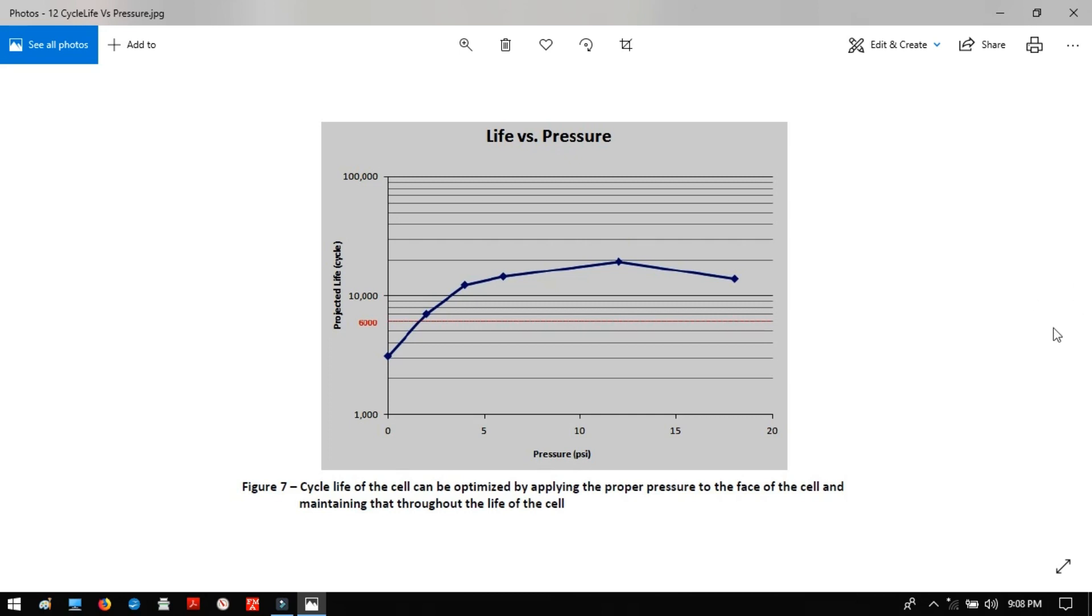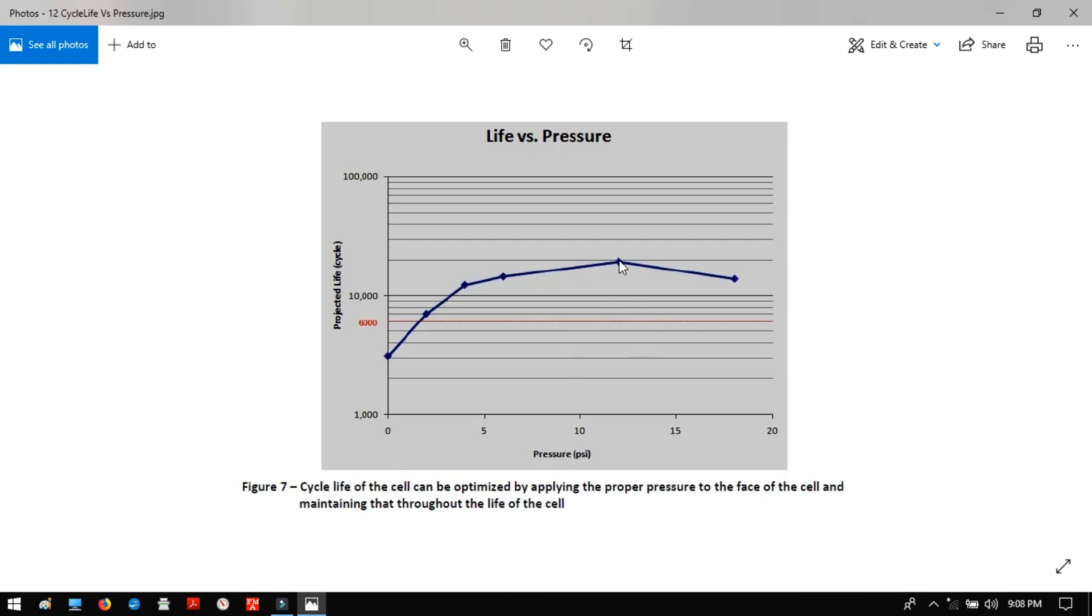And the last one I wanted to mention here is one that often isn't talked about too much, and that's the pressure. A lot of times these chemical reactions inside the cells in the anodes and cathodes and so forth has slight volumetric differences. And so in these pouch cells, these A123 lithium iron phosphates that I'm talking about here, we start off with so many thousands of cycles. But they actually, the anodes and cathodes and so forth, can physically change in size slightly as they get filled and depleted as the lithium moves back and forth. And if you do 0 PSI that you're pushing evenly on both sides of that slightly flexible pouch, then this is where you're at. Now, it's been tested that if you apply an even pressure across the entire face so that you don't have fractures and metal fatigue and all the other things that can happen inside the cell, then you can get more thousands of cycles out of it if you have that up to about say 12 PSI here. And then you start getting a detriment and it starts going down.